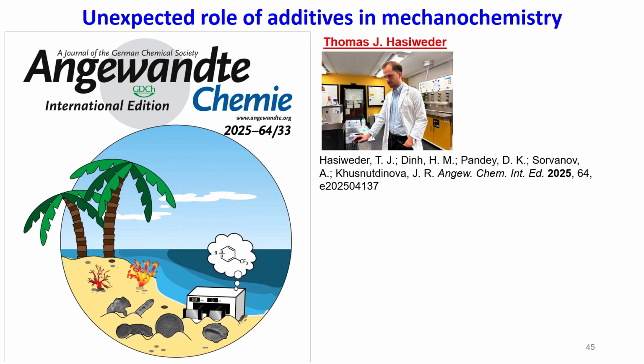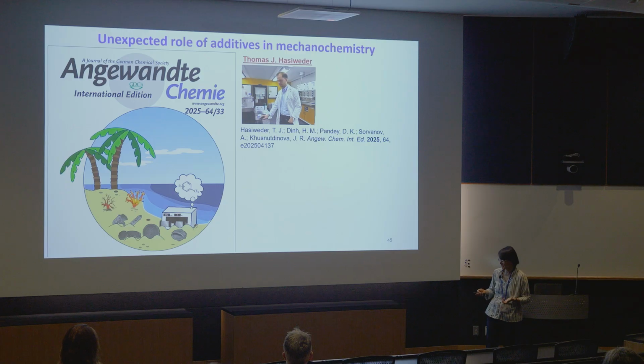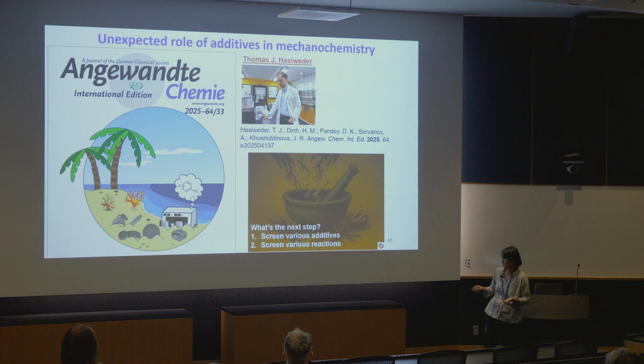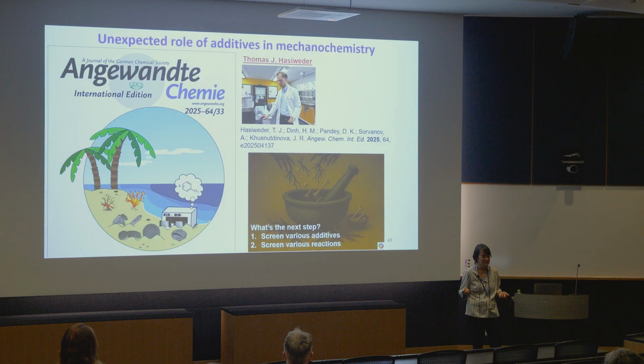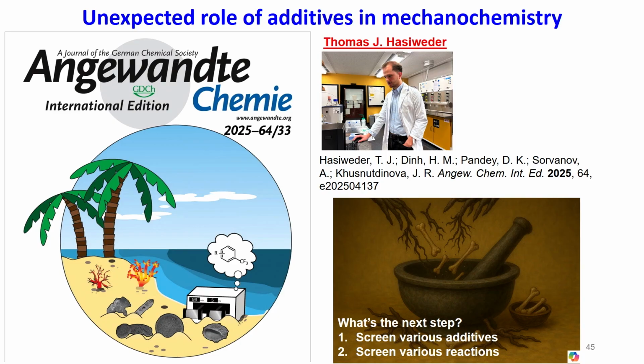So what would be the next step, right? Well, we could potentially screen different additives, something apart from zeolite, or we could screen different reactions. And we were working on both of these directions in parallel. When we started screening various additives, my lab almost turned into an alchemical lab. We would throw something like a mix of shells and bones and sprinkle it with volcanic ash from Sakurajima. Some of these additives worked, some of them didn't. It was completely inconclusive. And then we were expanding the scope of reactions, which is exactly where we had more success to explain the result.